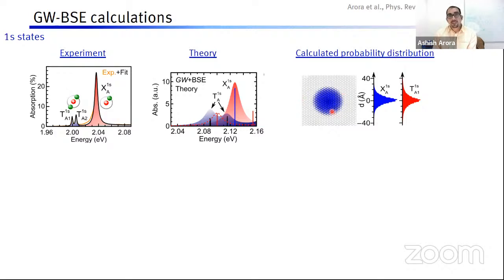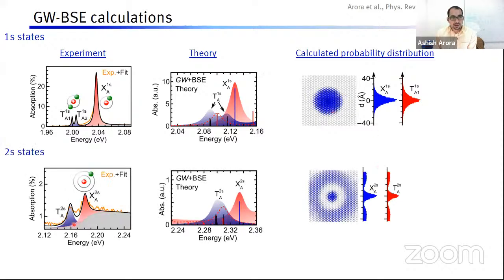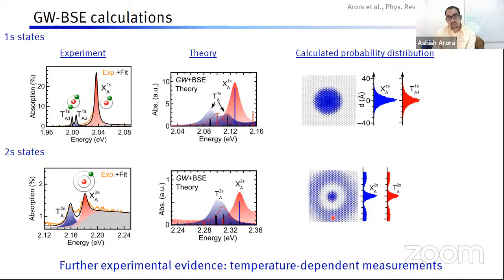Now, when they look into the excited states, what they find is that, similar to us, they have an excited state of the trion here and an excited state of the exciton, which has a probability distribution function similar to a 2s state of the hydrogen atom. Of course, this is not enough because we are experimentalists. We would do more. So then we try to see if what we are seeing in our experiments are actually 2s excited states of trions or not.